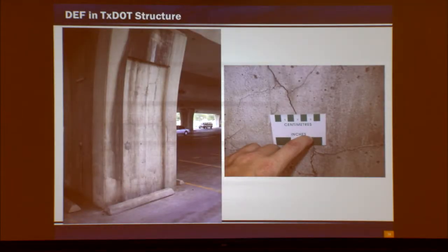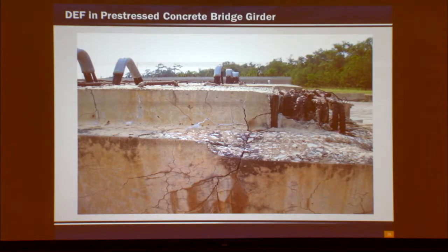This is a structure. I couldn't find the picture, but we actually dug out the footing of this thing, and you could stick your hand in the crack. That's how much expansion we actually had from DEF. Also in precast, it's been an issue because of high cement contents, trying to get early age strength. This is a girder that would have gone to Houston, and you see all the cracking that developed. That girder just sat there. It's never been in service. So we have had these issues in Texas.